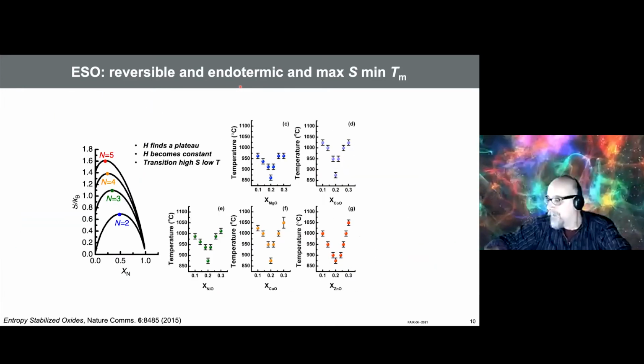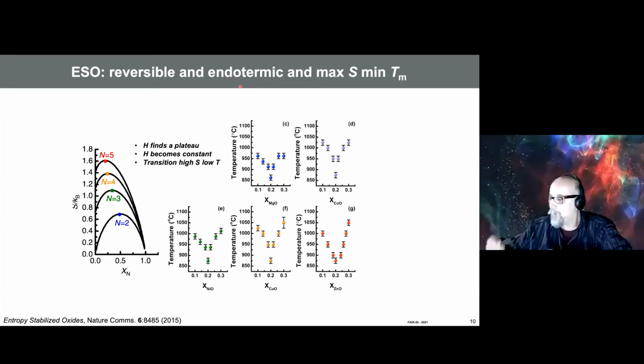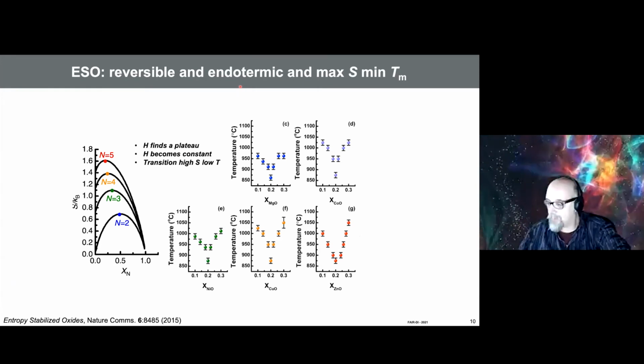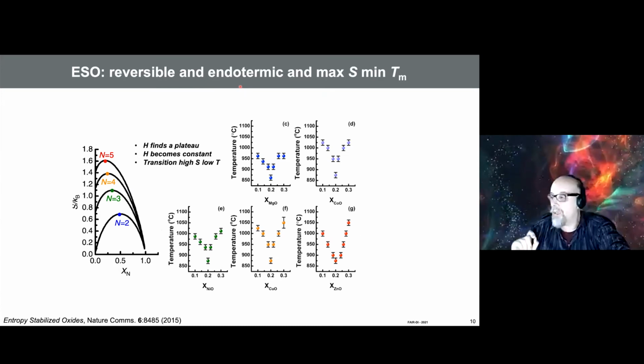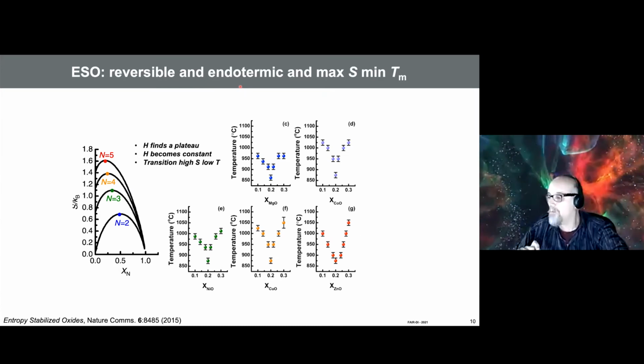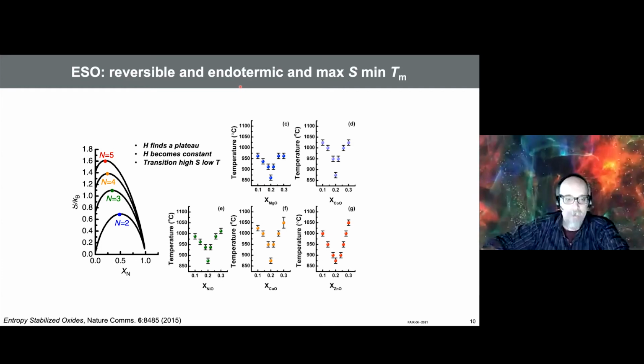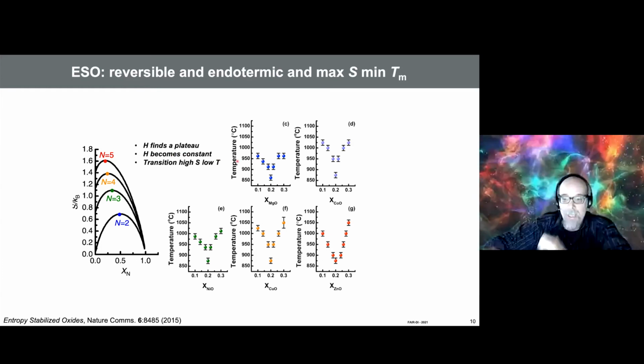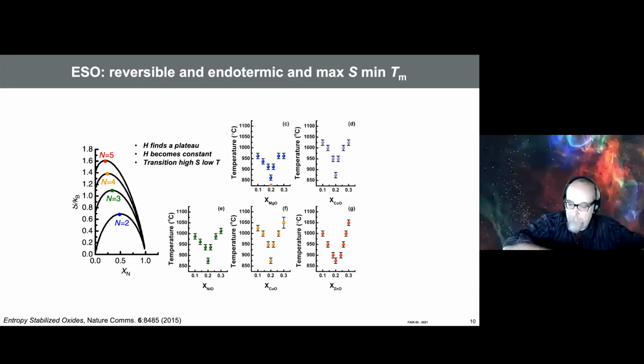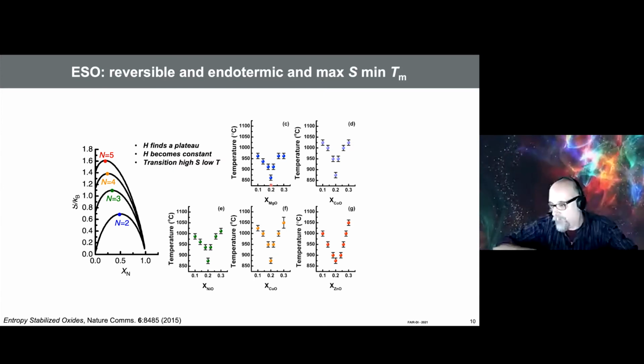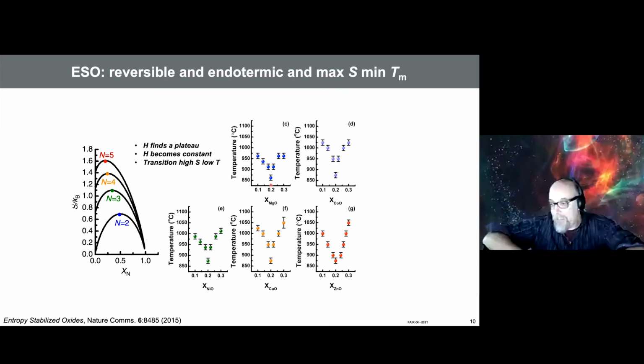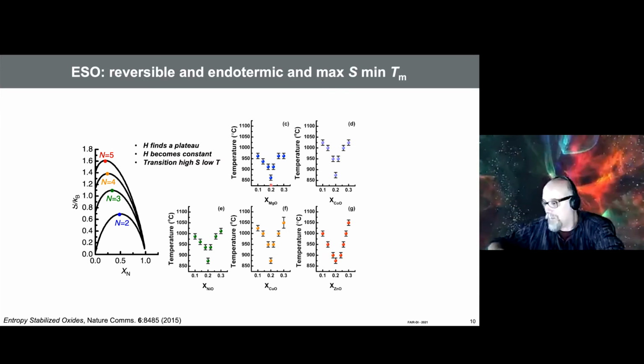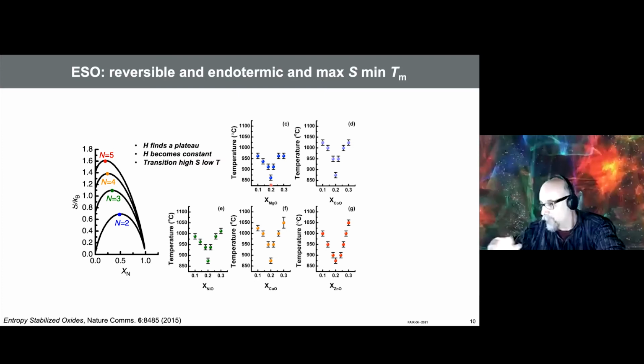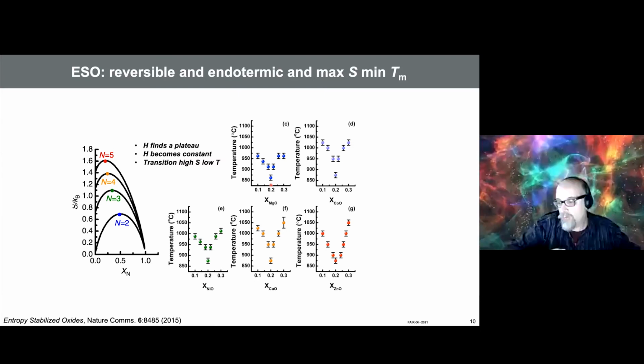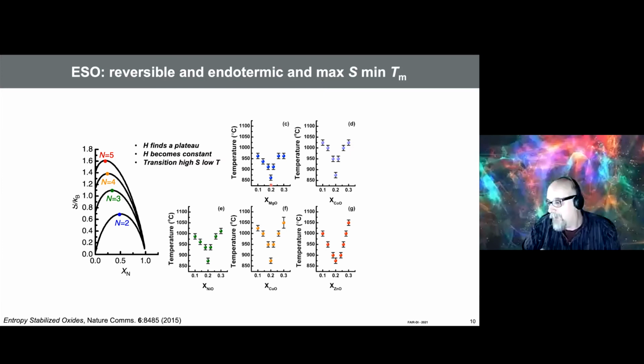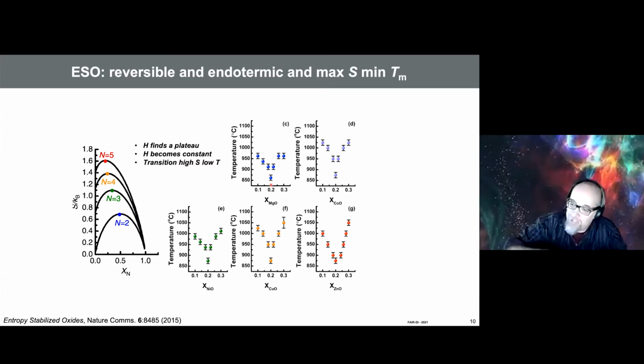And then another test, because people talk about entropy stabilization, entropy transition, but is it really entropy? You need to check where the transition temperature is with respect to entropy. So the best way to do it is actually very simple. If you are at equicomposition, maximum entropy is at equicomposition. So where S is max, T is min, because you are fighting against a constant enthalpy. We neglected it, therefore it's constant. So if you go off max S, then T will change.